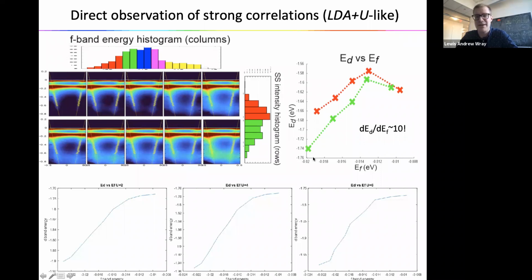As you dope the F electrons, as you shift the binding energy of the F bands by just a few meV, just on the scale of 10 meV, you find that the D bands shift by, these are measurements for different surface terminations, on the order of 100, 150 meV. That's exactly what you expect, because the F electrons are the ones that are strongly correlated. They're the ones that don't want to be squeezed on top of one another.